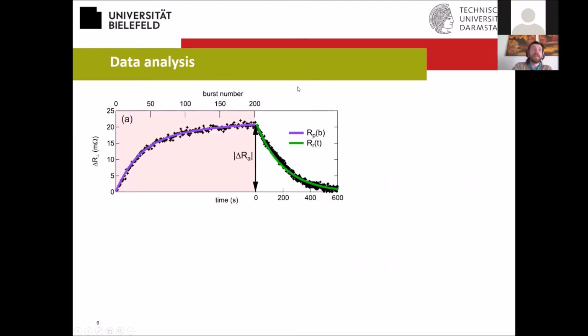How do we do the data analysis? We have basically 2 phases in our experiment. The first phase is the pulsing phase, where we increase this transverse response. And then we have this relaxation phase. So here our x-axis is the burst number that we send in. A burst consists of a number of pulses that we send in. And then we have this relaxation phase where the x-axis is simply time. We define this value here as the switching amplitude, or RA.